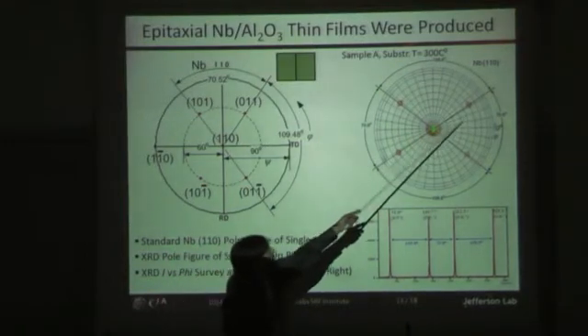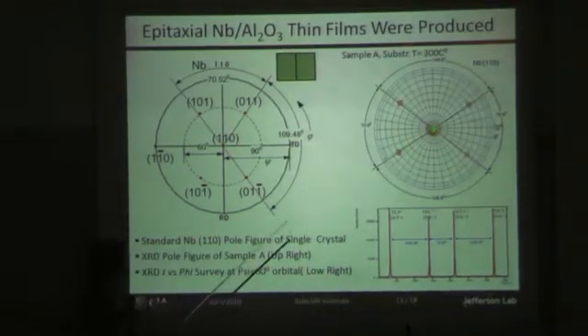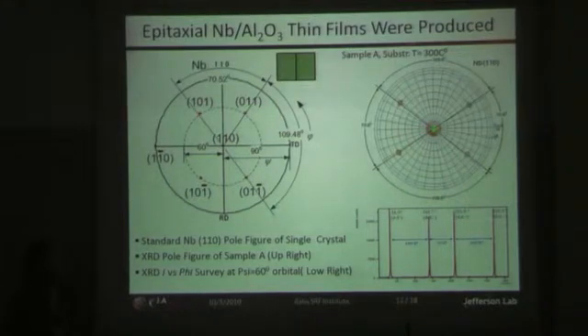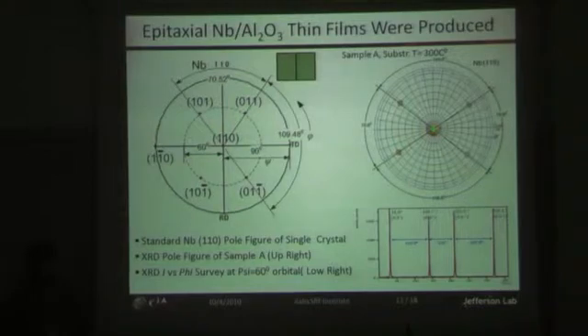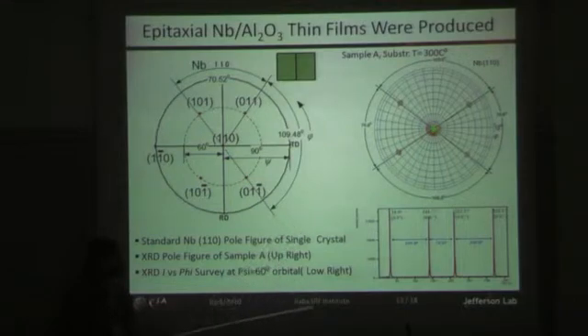This is experimental data, and what we're finding is that these two neighbors are 70.8 degrees apart and these two neighbors are 109.8 degrees apart — in excellent agreement with theory. The pole figures are giving us an incredible amount of information beyond the theta-2theta scans, and it's a very valuable tool. I would urge anyone exploring their thin films, if you have access to pole figures, to definitely look into your films, as they can provide more information.